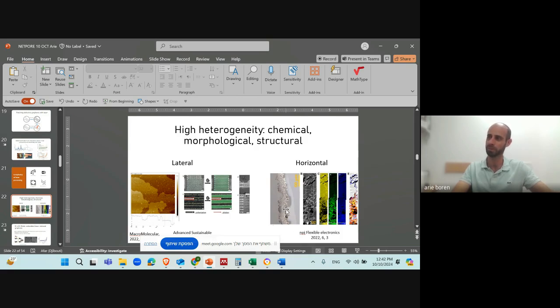And now you see that we wanted to see the changes in chemistry throughout the depth of the film. So we see the carbon, nitrogen, oxygen content. Nitrogen, and also oxygen, but for sure nitrogen, is almost entirely on the lower part of the film. The upper part that gets all the heating from the laser, all the nitrogen is eliminated. So this is why you have a very complex film, and the porosity is very different throughout the depth of the film. So it is very heterogeneous chemically, and also the structure is very heterogeneous.